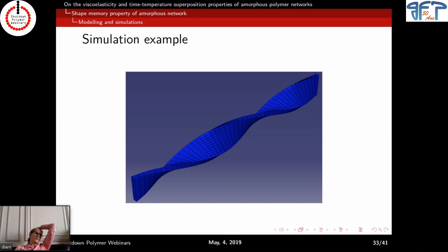You mean, can you imagine a polymer that will fix the torsion shape instead of memorizing the rectangular shape? Well, for this material it's always the initial shape that you're going to recover. So it depends on the initial shape you give to your material, right? So you could do whatever you want with them, especially now with 3D printing. But what's true is that to apply another temporary shape, you need to apply stress.